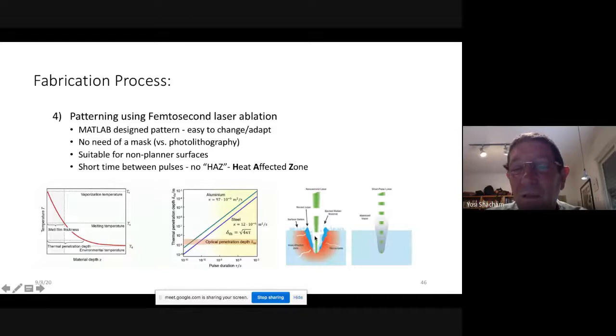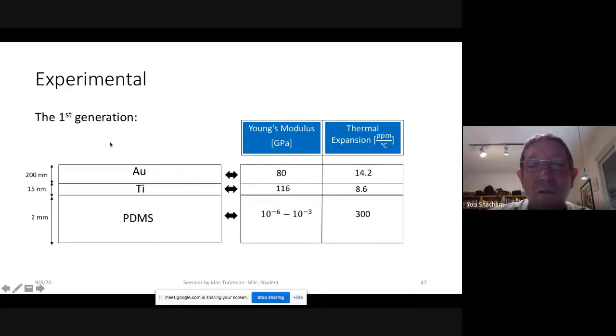If you have a nanosecond pulse, you're heating the structure, and the heat, this red zone, is propagating. If you have femtosecond pulses, you are ablating the material, but the heat is not propagating, because the time is so short. The diffusion length of the heat, which is the square root of diffusivity times time, is so small, maybe a few angstroms, so there is no heating, only ablation. Because of that, we get a much cleaner cut and much nicer structures. And the first generation structure is gold, titanium and PDMS.